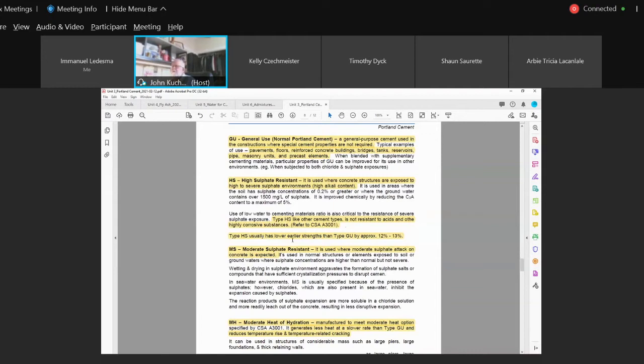The HS will usually have lower strengths than GU at the earlier age, but at 28 days shouldn't have a problem. Typically on a GU cement, within 7 days you should get 70 to 75% of your 28-day design strength. Whereas if you're using HS, high sulfates, typically you might only get 65 to 67%. So don't panic if your HS cements are typically lower than what you're used to with pavement. It's because of the composition. When you work with concrete and understand the basics, you can understand it.